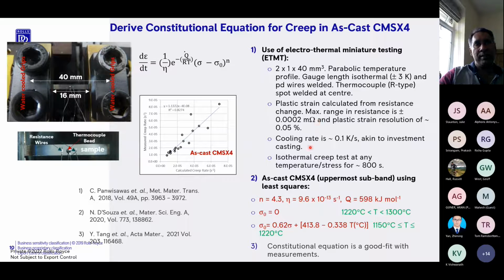We use a typical cooling rate akin to the cooling rate used in investment casting. And like I said, these are non-isothermal creep tests, but they're isothermal for typically about 800 seconds. Traditionally you would call them non-isothermal because they are very different from a traditional creep test that will run for several tens of hours at a given temperature. In this case, they're at best isothermal for about 10 minutes. So I would say they're isothermal creep tests, but for about 800 seconds. But if you want to look at it in terms of a traditional creep test, well, you can call them non-isothermal.